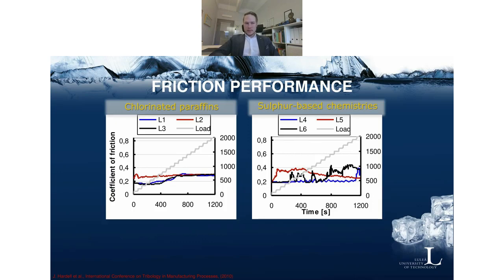We also had a couple of sulfur-based chemistries that we evaluated as replacements for this. And as you can see, the lubricant chemistry plays a very significant role in terms of the frictional stability that it can induce on the system. So some of them showed a relatively high friction, some showed an unstable friction, but there were actually some, the blue one in this case, L4, that showed a promising behavior with even lower friction at higher loads compared to the chlorinated paraffin chemistries.